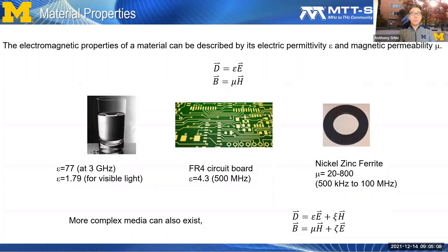In general, the electric and magnetic properties of a material can be described by two material parameters, or fudge factors, permittivity and permeability. For example, a glass of water has a permittivity of 77 at gigahertz frequencies, which falls off to about 1.79 at visible wavelengths. Commercial circuit boards, on the other hand, have a permittivity of about 4. Ferrites, like those found at the ends of computer cables to prevent unwanted irradiation, have magnetic responses with permeabilities of 20 and beyond. Materials with electromagnetic or magneto-electric parameters can also exist.